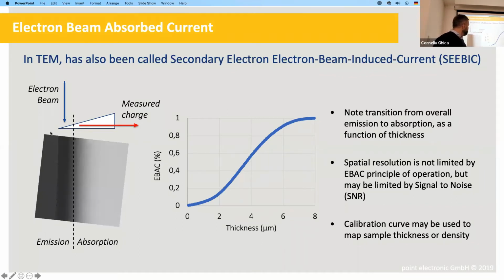What is happening is that when the sample is very thin, we have mostly emitted electrons. The primary electrons go through the sample and are not really absorbed in great proportion. They also excite more electrons and move more electrons out of the sample, so overall we lose electrons from the sample, and we extract electrons from our circuitry. Whereas when the sample is thicker, absorption is dominant, so we have more absorption than emission. If we plot the EBAC signal as a function of thickness, which we can do because it's a wedge, we can see there is a relationship between the two, and there is a saturation and so on.